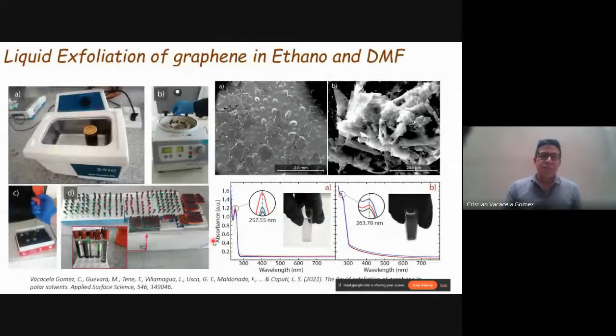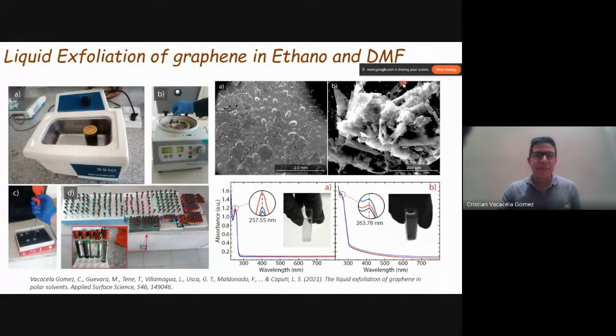In our case, for example, in this work, we analyzed more than 300 samples prepared by using bath sonication in ethanol and dimethylformamide. So to understand what the parameters are that we can control to optimize the production of few layer graphene or graphene nanoplates by using the liquid phase exfoliation process.